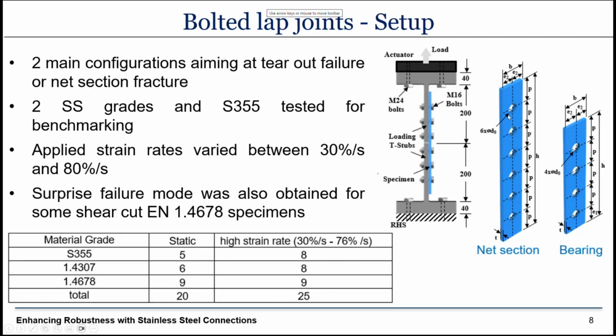So for all configurations, we tested both stainless steel grades, and we also tested conventional carbon steel S355 lap joints for benchmarking. The applied strain rates varied from quasi-static up to about 80% per second, which gave us, according to the material tests, the biggest detrimental effect in terms of reducing the ultimate capacity.